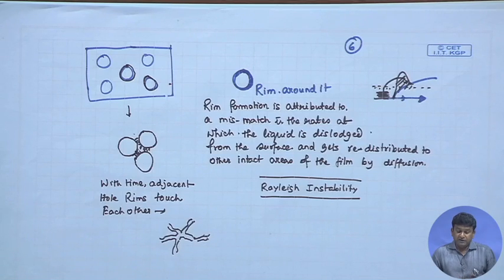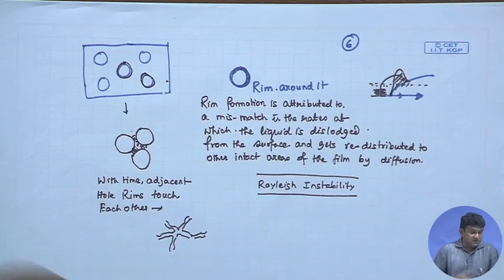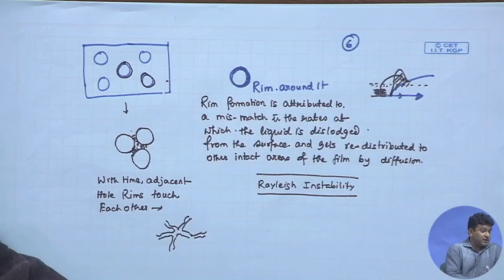It turns out this rim profile gives a lot of idea about the viscoelasticity of the film. If you have a long chain polymer, which is more viscoelastic due to entanglement effects, the rim profile becomes very skewed. It becomes very sharp on one side, while inside and outside it is pretty slanted. I will skip all the details for the time being.